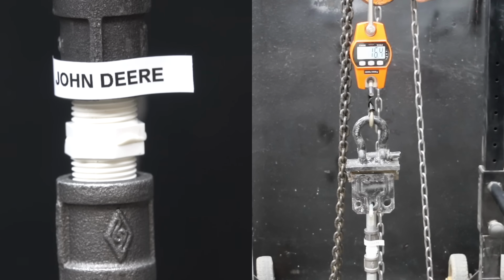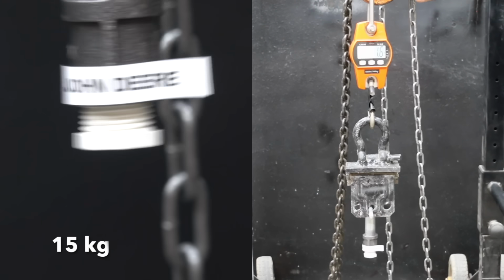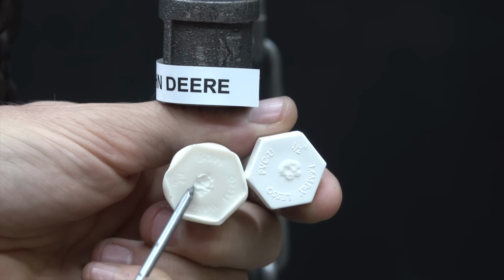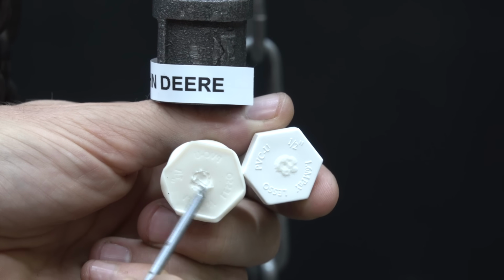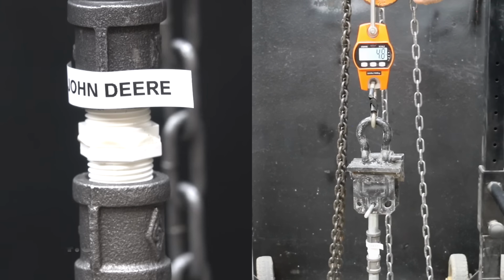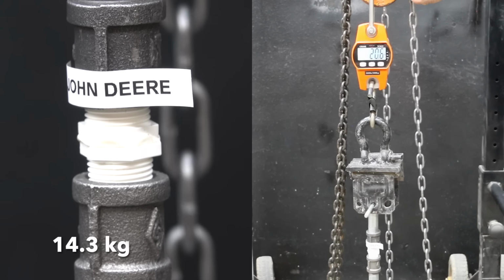And the John Deere RTV gasket maker gave up early at only 33 pounds on the first test piece. Even after 72 hours, there's still a small area that did not fully cure with the John Deere brand. And the second test piece did almost the same as the first at 31.6 pounds.